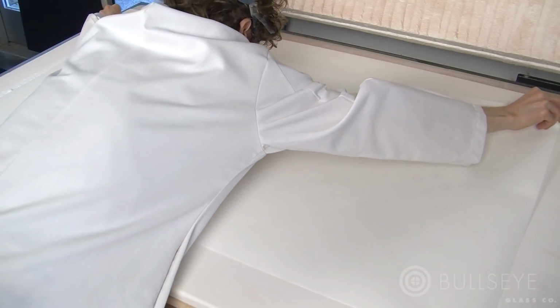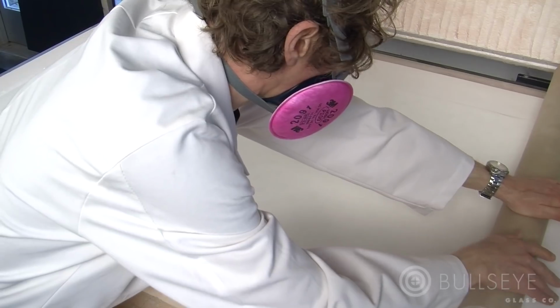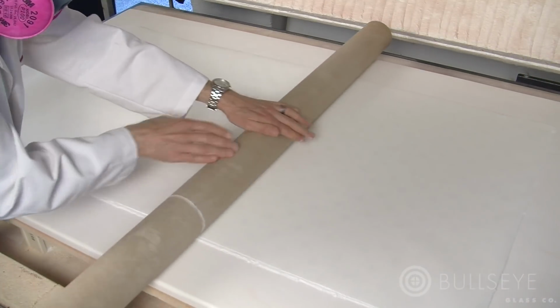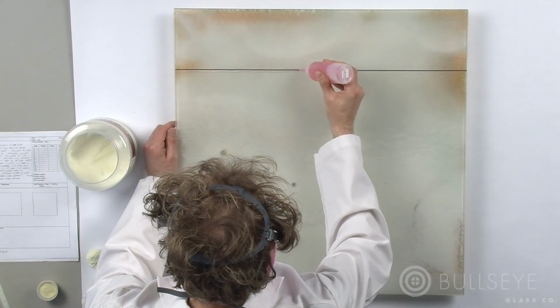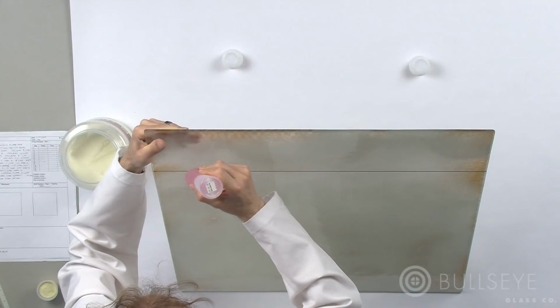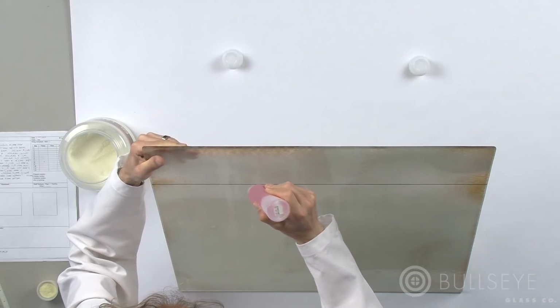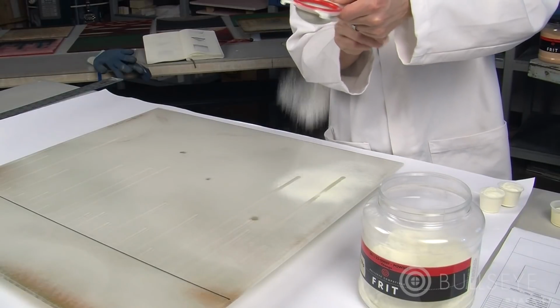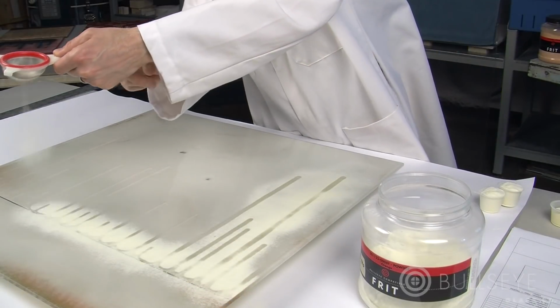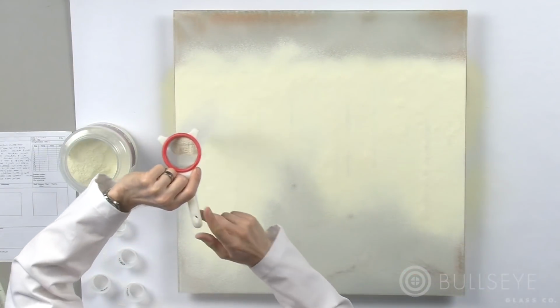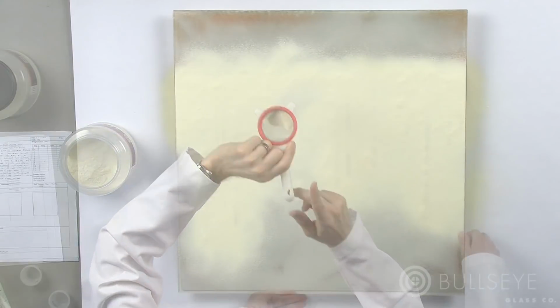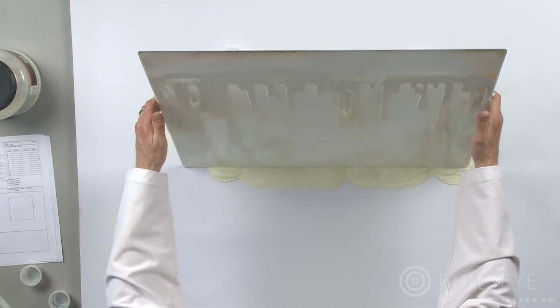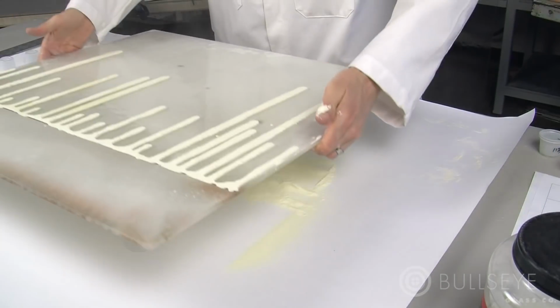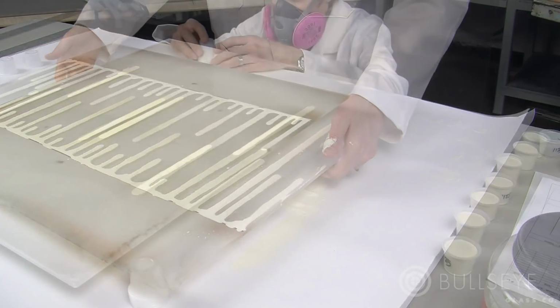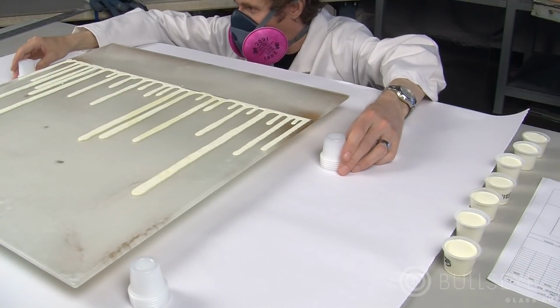I then put down a fresh piece of thin fire, and I roll out the whole thing, so I've removed any bumps in it. And I'm just working on the back side of the first piece that you saw. I put down holding agent, and I run it along that line I've drawn, and then I let it drip down. And then I'm going to cover all of that up with 8 cups of 1125-08 orange powder. I then knock it off of there, and I actually end up reclaiming about 7 cups of material. So only one of the 8 cups actually stuck to that.